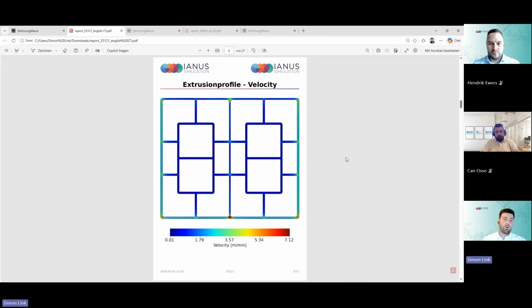So basically the most important plot is the one here for the velocities, as you can see here at the exit of the die. And the scale here shows the velocity. So blue is almost velocity of 0 meters per minute, and red is a velocity of around about 7 meters per minute. And what we see is that we have very low velocities in the middle of the profile, and on the outside we're having much higher velocities, and on the top there are also very small velocities.